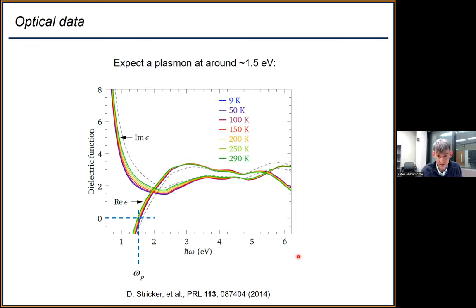Okay, so let's suppose you just were to guess what you would expect to see in strontium ruthenate. Strontium ruthenate's a metal. You probably would expect to see a plasmon. So where do plasmons appear? Well, plasmons show up normally where the real part of the dielectric function crosses zero. So the dielectric function of strontium ruthenate has been measured. It's in this paper. And the real part crosses zero at 1.5 eV, something like that. So you might expect to see a peak at about 1.5 eV.